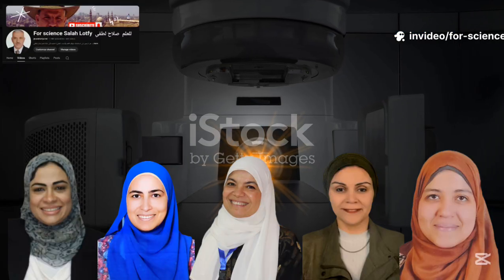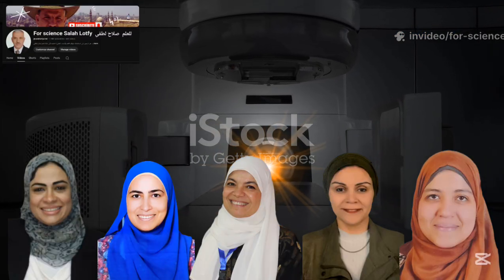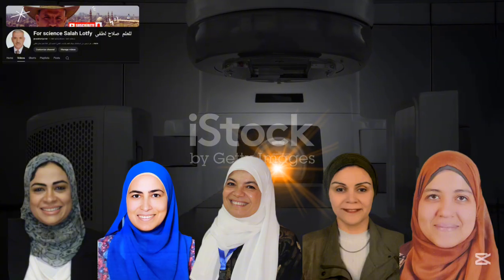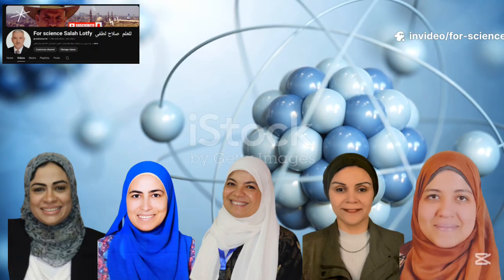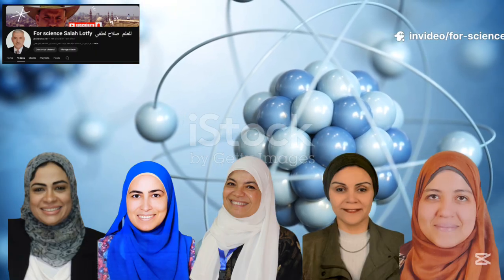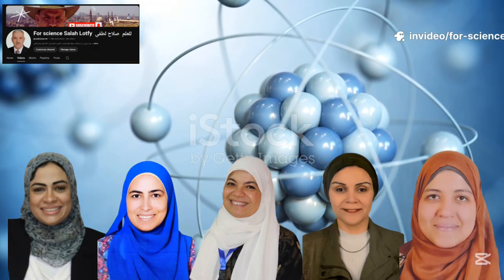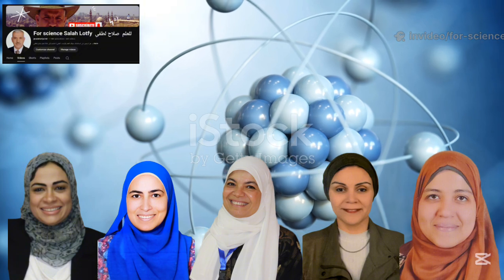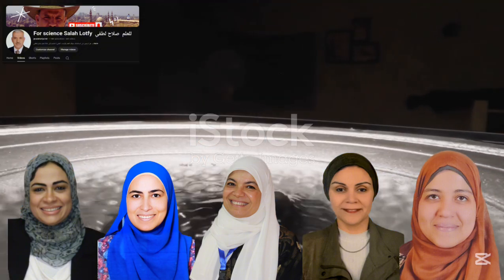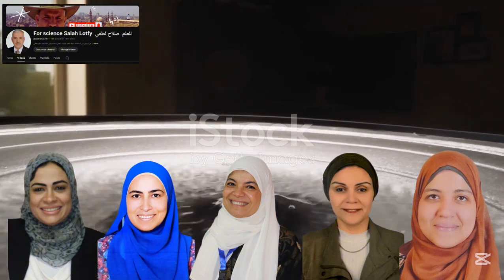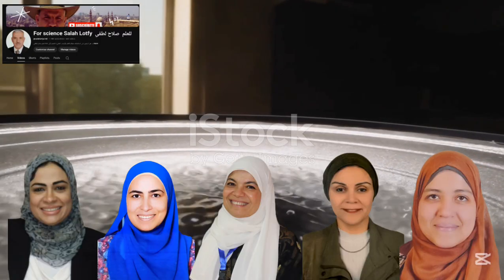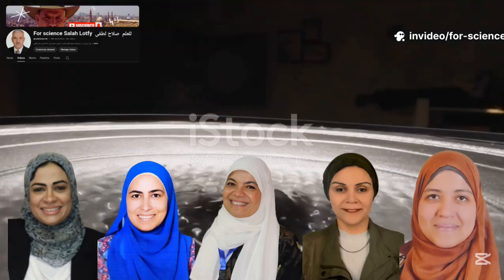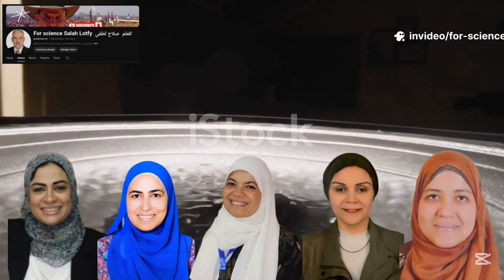The National Center for Radiation Research and Technology, NCRRT, part of the Egyptian Atomic Energy Authority, provided the electron beam irradiation facility. The accelerator operated at 3 MeV, with a beam current of 10.3 mA, and a scanning velocity of 3.39 meters per minute. This irradiation technology was used to cross-link polymers into hydrogels, and simultaneously sterilize the samples, an eco-friendly process with no chemical residues.